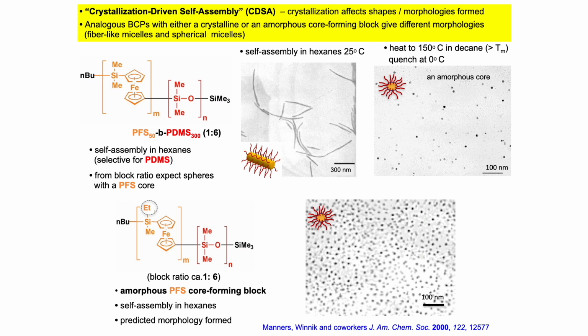So what this shows, really for the first time, is that crystallization of the core forming block can affect the self-assembly. So we call this crystallization-driven self-assembly. Crystallization affects the shape you get. And what's nice here is spheres are very easy to make, but fiber-like structures are very difficult. And you get a pure fiber-like morphology here - they're all fibers.